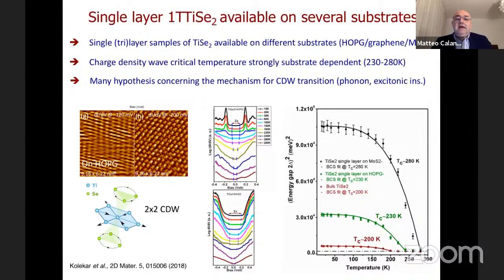And for example, only very recently, due to the strong reactivity of the system, single tri-layer samples were actually obtained on different substrates. For example, HOPG, graphene, or MoS2. And you can see the samples are fairly large.